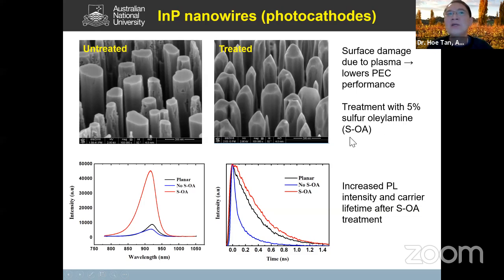Okay, and if we treat it for about an hour to an hour and a half, after that you can see the surface is properly cleaned up without any surface damage. In addition to that, we did the measurement. You can see this is the photoluminescence coming up from the nanowire. After the sulfur oleylamine treatment, you can see this luminescence is significantly enhanced, which means the quality now has improved.